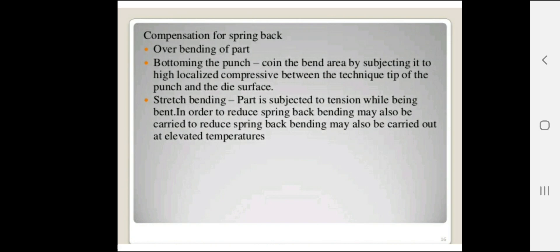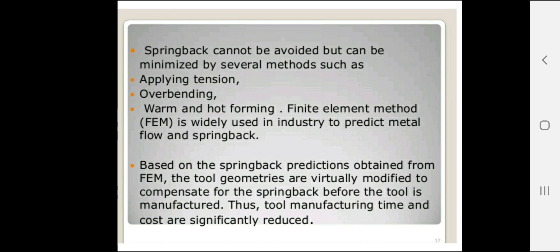In stretch bending, the part is subjected to tension while being bent in order to reduce spring back. Bending may also be carried out at elevated temperature to reduce spring back. Spring back cannot be avoided but can be minimized by applying tension, over-bending, warm and hot forming. The finite element method is widely used to predict metal flow and spring back; tool geometries are virtually modified based on FEA predictions, significantly reducing tool manufacturing time and costs.